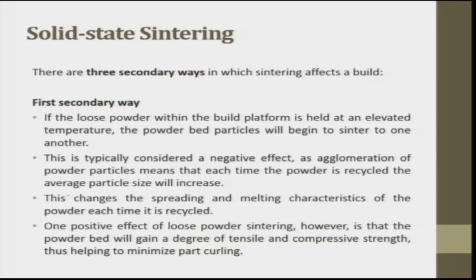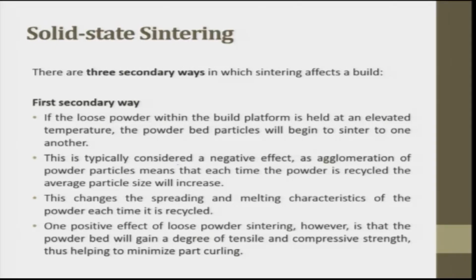So you can't keep maintaining it at a very high temperature. After some time, you have to maintain a slightly lower temperature such that it does not sinter. This is typically considered a negative effect, as agglomeration of powder particles means that each time the powder is recycled, the average particle size will increase because it is all getting stuck. This changes the spreading and melting characteristics of the powder each time it is recycled.